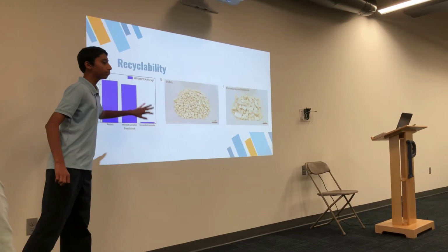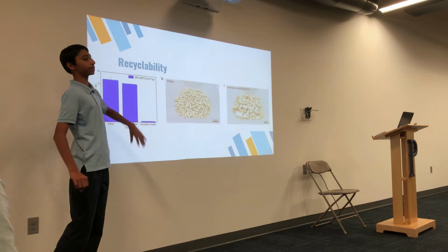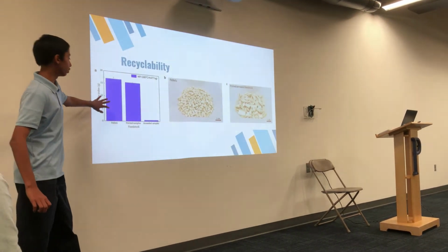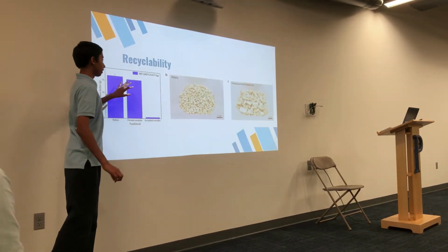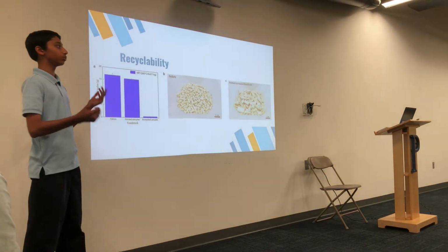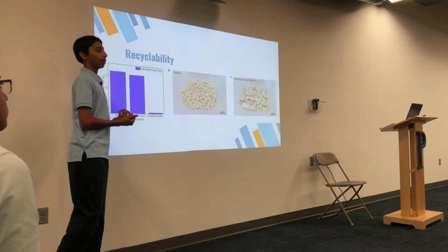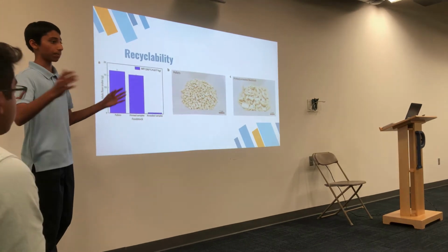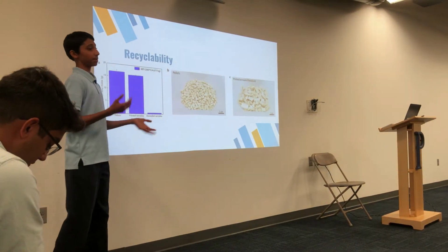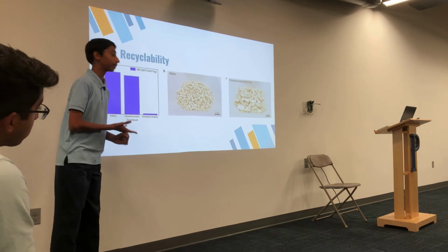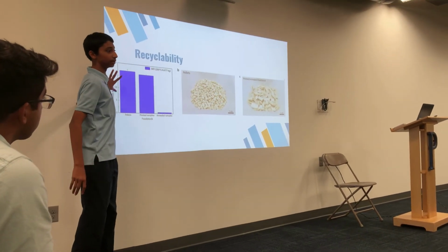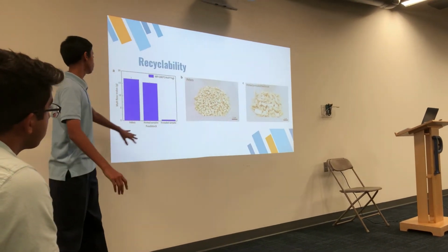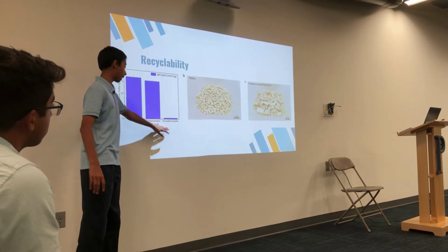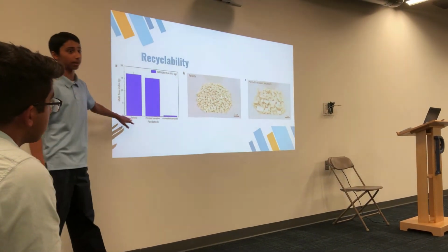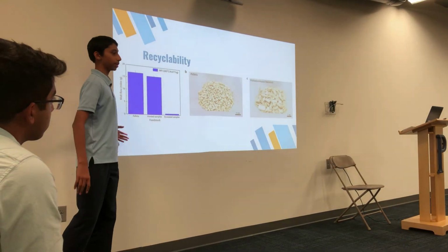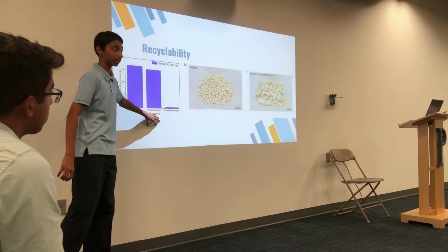But you can reclaim, because the annealed samples have so much more strength than just normally printed samples, they determined that if you were to perform a hydrolysis reaction, which is you add water to break apart the molecules further, and then maybe some other enzymes as well to catalyze that reaction, you can regain this amount of recyclability. So this may look dismal, like this is really not recyclable, especially compared to the same material just not printed and printed without annealing.